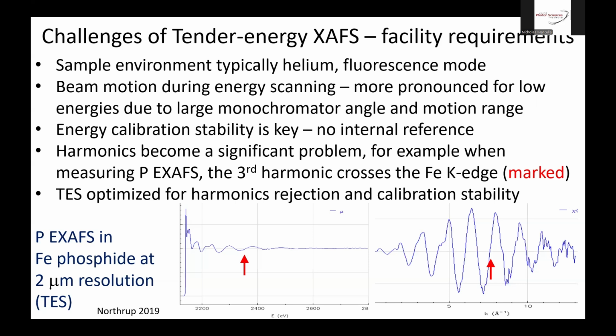You really need to reject the harmonics even down to low energies. And that requires having mirrors in the beamline at fairly steep angles, like 10 or 12 milliradians, which is really unusual. So the TES beamline was optimized for the harmonic rejection. Its harmonic rejection was better than 10 to the minus 5, which is really good, as well as calibration stability. So this was a measurement made at TES on an iron phosphide at 2 micron resolution. So this combines all of the different requirements for a difficult experiment, and it succeeded.